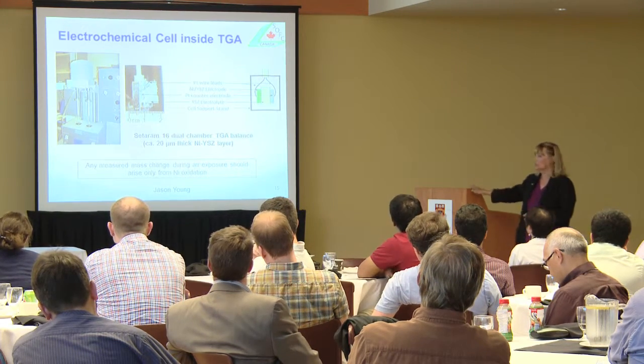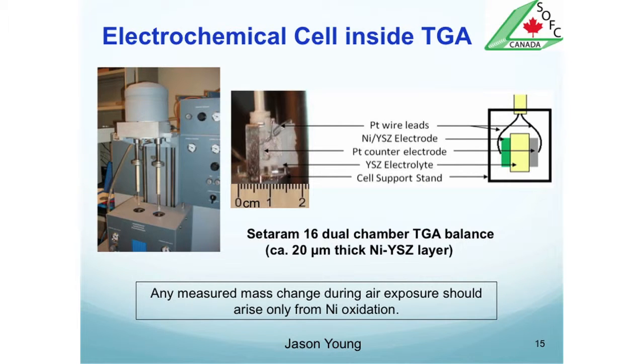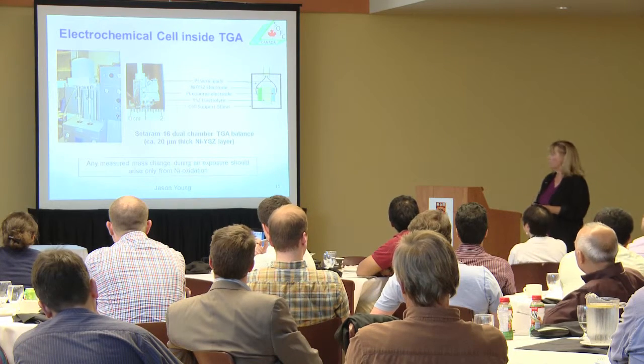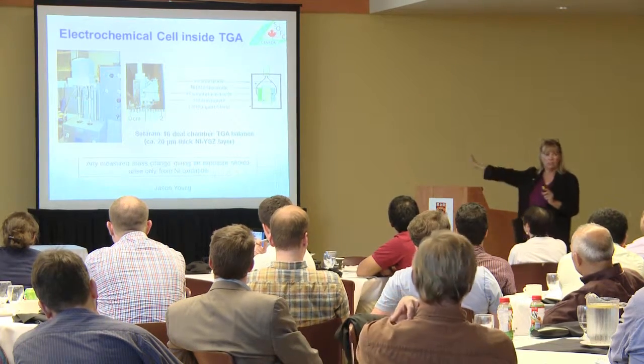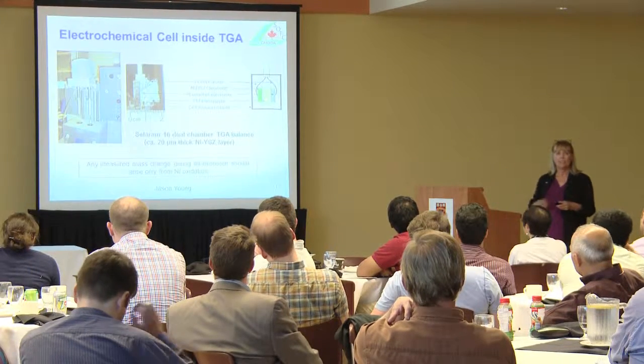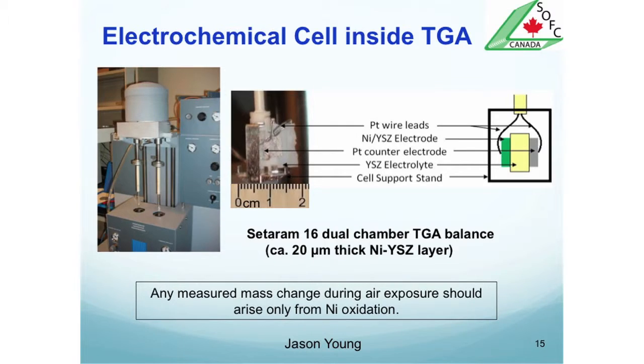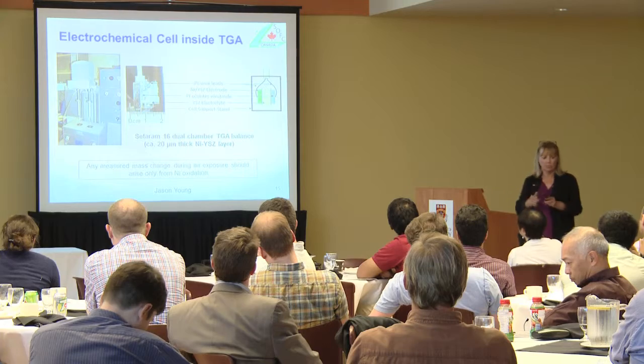What he has constructed is a means by which you can put a little baby cell into a TGA, thermogravimetric analysis, to measure mass at high temperatures, in various atmospheres. And he managed to do this very nicely, actually, and he used conditions and materials, as you see here. We assume that any mass change we see has to come from the nickel. Platinum should be inert, we think, under these conditions. YSZ should be inert. So we assume any mass changes we see, it's nickel oxidation or preventing nickel oxidation.